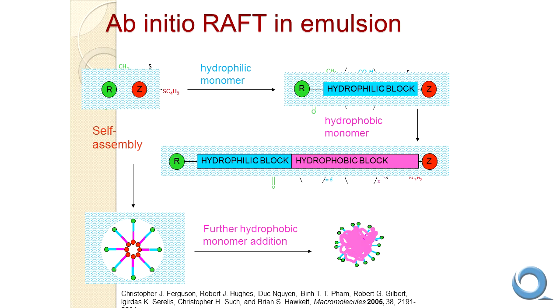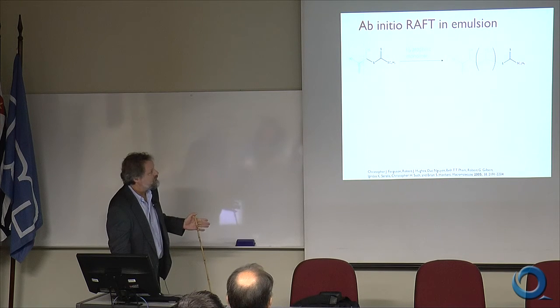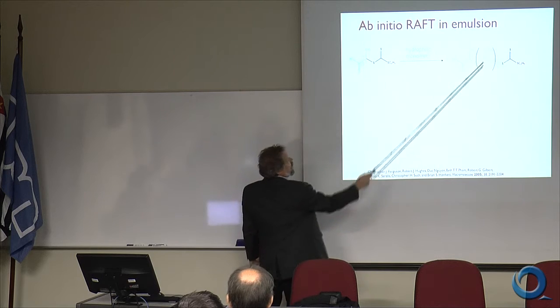We use this process in a technique called ab initio RAFT emulsion polymerization. It was developed in Australia at the CSIRO, which is one of their national laboratories. And the same idea, we start with this chain transfer agent, but we start with a hydrophilic, ionic monomer, and we form a hydrophilic block. So we form a hydrophilic ionic polymer, which is a living polymer with the chain transfer agent end at this end.